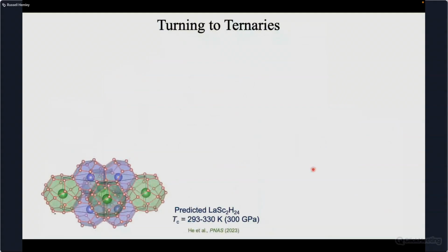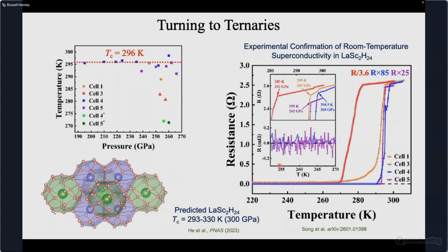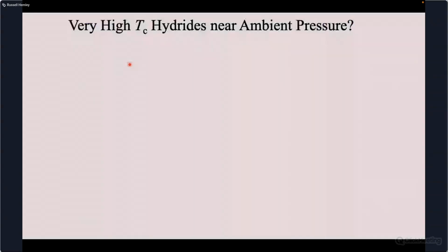So I also want to come back to this prediction of lanthanum scandium-2 H24 and work done by our colleagues at Jilin University. They in fact have confirmed this prediction in a remarkable paper that's on the archive. Here we have the resistance data. They've done a number of different measurements, including magnetoresistance measurements. And what they see in a number of runs is a TC right around room temperature, albeit at somewhat higher pressures than the work on pure lanthanum hydride, more like 250 GPa, but right around room temperature. So this is an exciting result. Again, a confirmation of the DFT predictions.